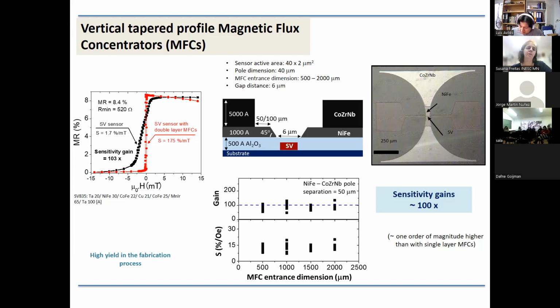And sometimes, if the process goes wrong, we may have, for example, in a batch of 20 wafers, 5 of them that do not work at all. Because during the etching, the process for TMR is much more complicated than for GMR. For TMR, we have several lithography steps. If we have double contact, normally this is what the industry requires. So from these 7 lithography steps, there are 2 or 3 that are high risk. And sometimes if we fail one of them with low yields, then it propagates to the full wafer, and then we have a wafer that is almost non-functional. So the TMR is really an expensive technology, and it's expensive to have a high yield and provide a reliable number of wafers, one after the other.